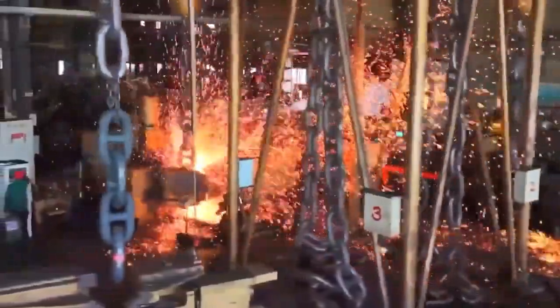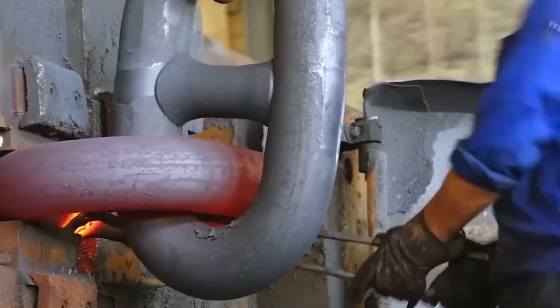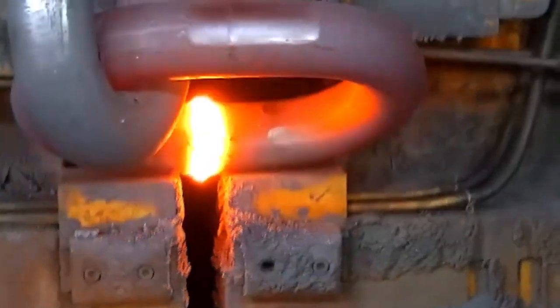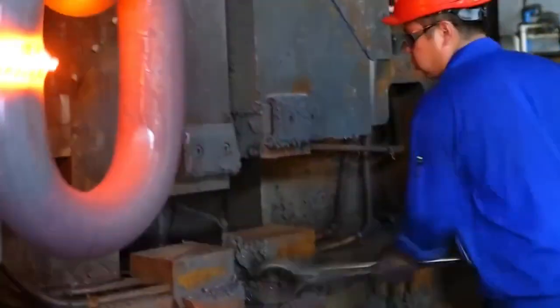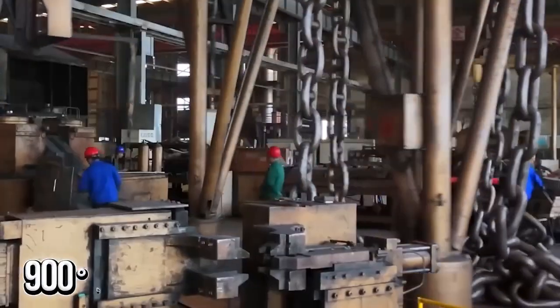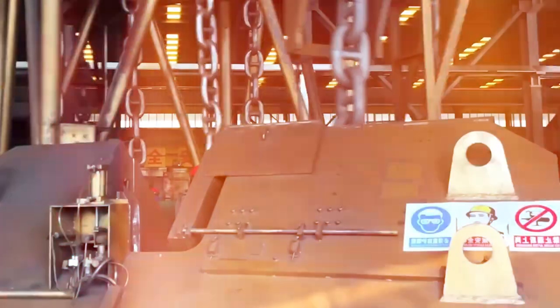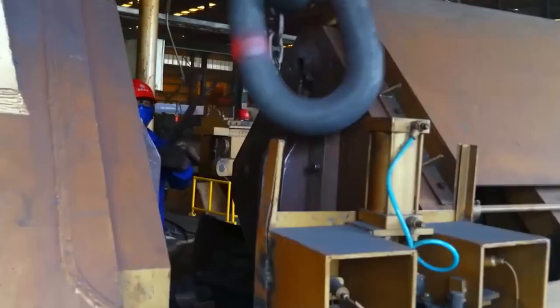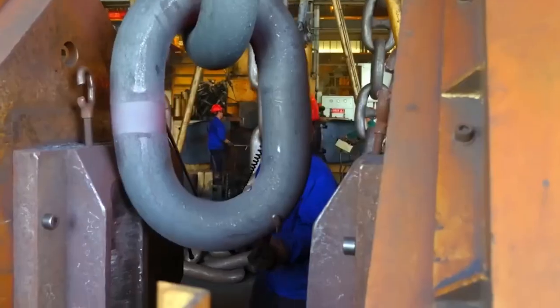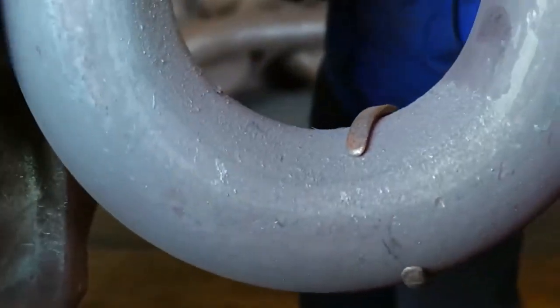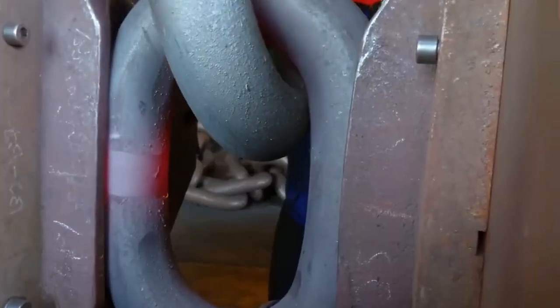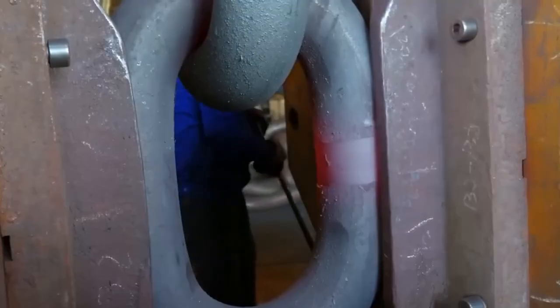The links enter controlled atmosphere furnaces for quenching and tempering, a two-stage process. First, they're heated to a precise temperature, usually around 900 degrees Celsius. Then they're rapidly cooled in oil or polymer quench tanks. This locks carbon atoms inside the iron crystal structure, creating martensite. Martensite is extremely strong, but too brittle for marine shock.